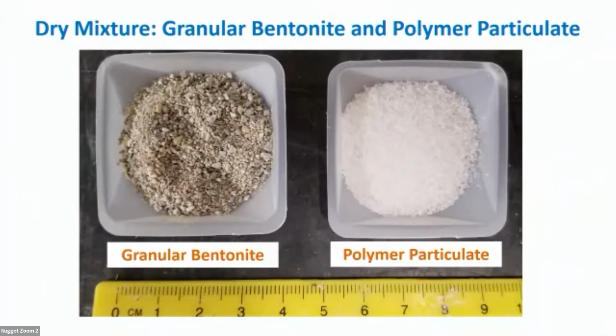Just to give you a sense for what the materials look like, that's very simple. We've got a granular bentonite on the left. It's a conventional bentonite that would be used in a geosynthetic clay liner. And then on the right, it's a commercially available hydrophilic polymer that you can buy from just a conventional manufacturer. These two are blended together using a screw auger. You've got a screw auger and distributor bar on an assembly line. You've got two geotextiles that are running across with the bentonite and the polymer being laid down in between. They're brought together and then they're needle punched to create that carpet-like product that you saw earlier.